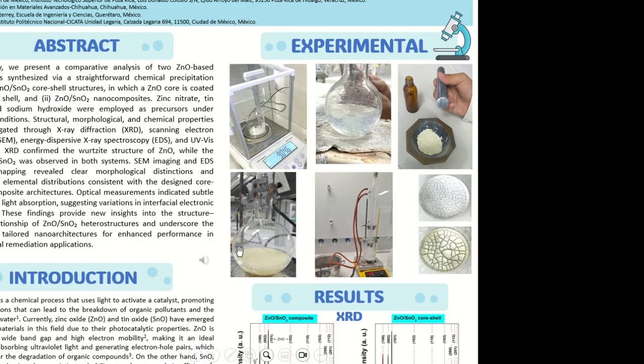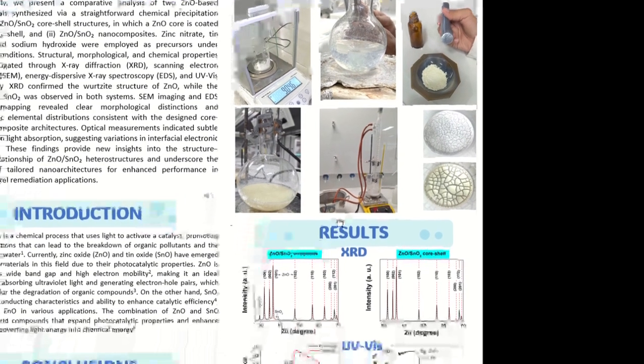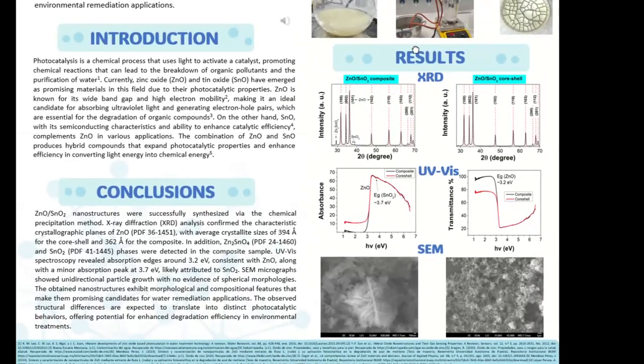To do this, 1 gram of the zinc oxide obtained was dispersed in a sodium hydroxide solution, 1.5 grams in 50 milliliters, using magnetic stirring. 0.19 grams of dihydrated tin chloride was added, and the mixture was refluxed for 4 hours at 90 degrees Celsius. The precipitate is washed either by decantation or centrifugation with water 3 times. The material is dried at 110 degrees Celsius overnight and calcined at 400 degrees Celsius for 4 hours.